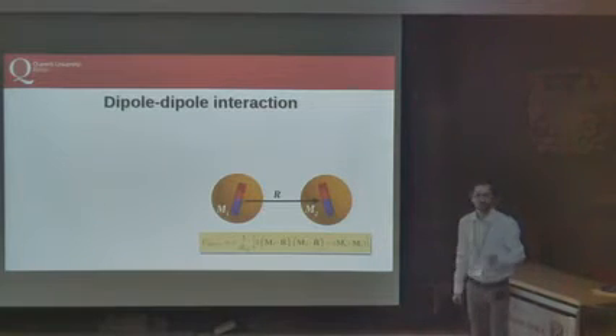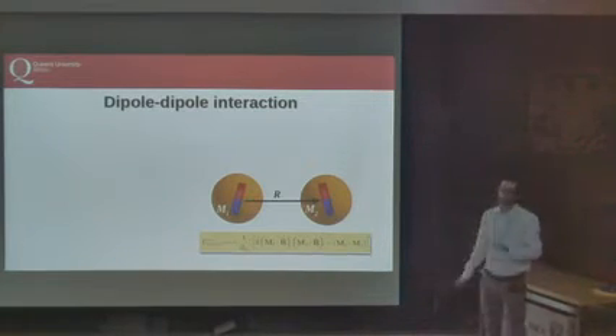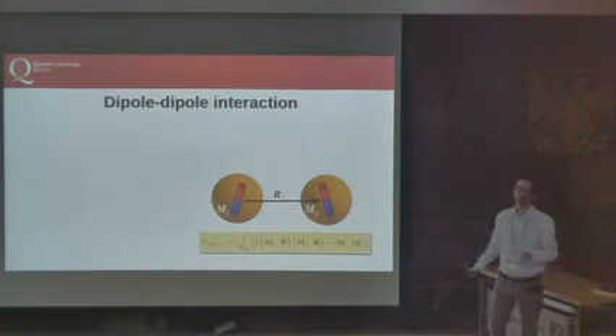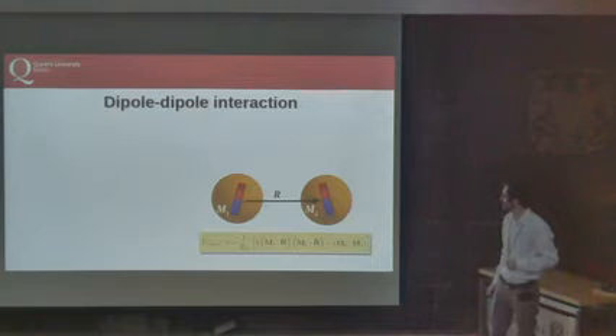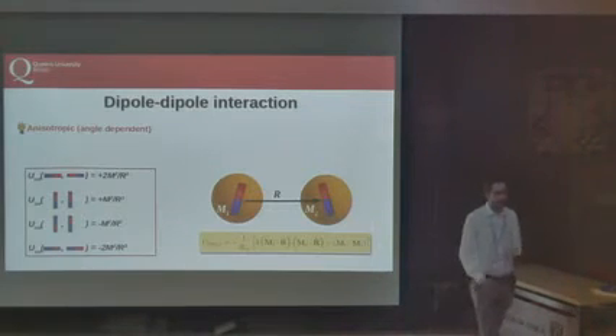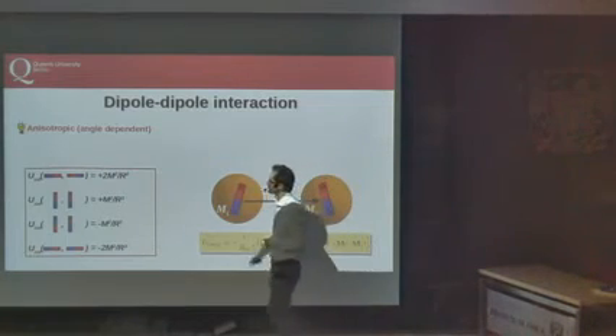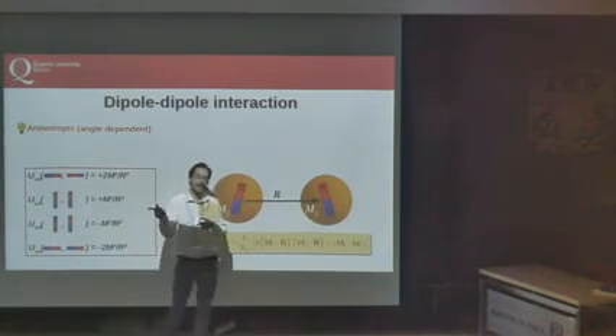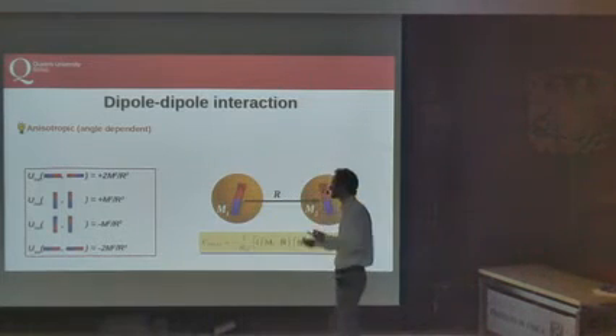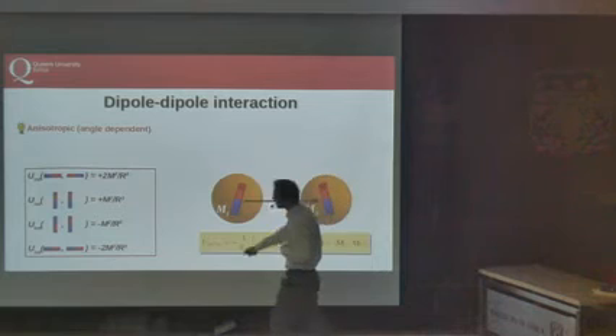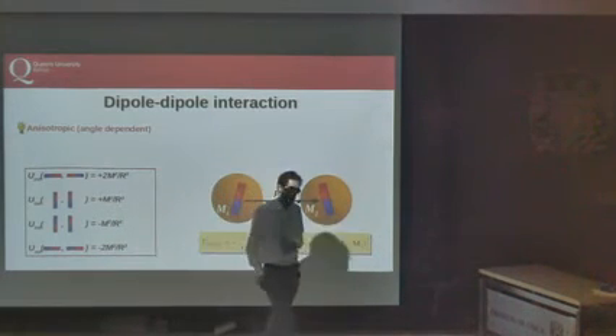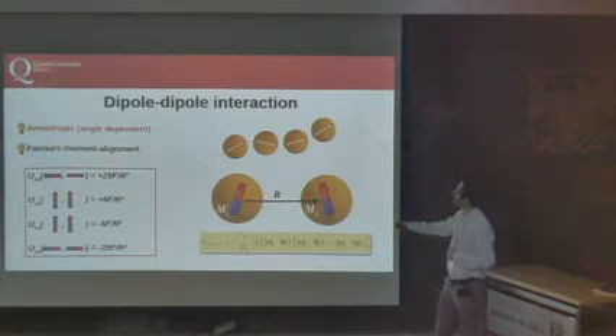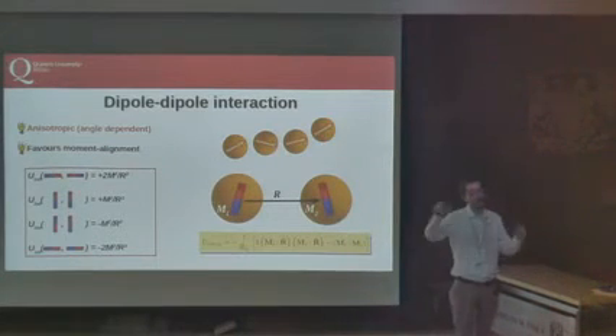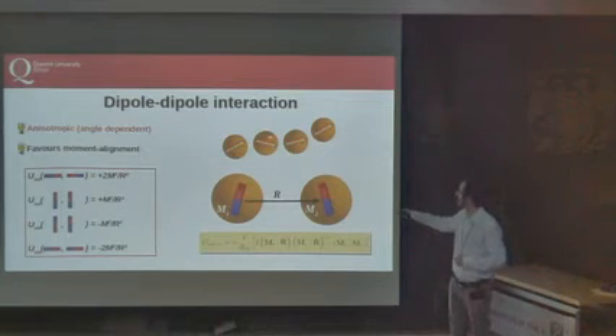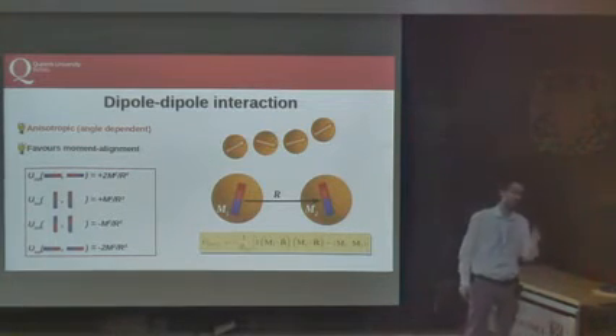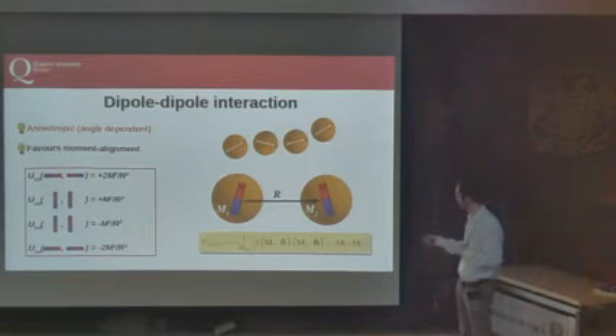First of all, dipole-dipole interaction. This is an interesting interaction, again, drawing from the previous analogy. Each nanoparticle is a tiny magnet. The dipole-dipole interaction is anisotropic, so the energy depends on the angle and orientation between the nanoparticles, and the distance, of course, and it favors alignment of nanoparticles. Of course, in solution with thermal random motion this will not be a perfect alignment, but this kind of configuration minimizes, or tries to minimize, the magnetic internal energy.